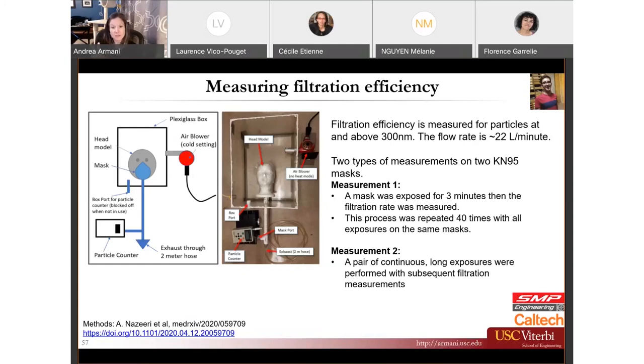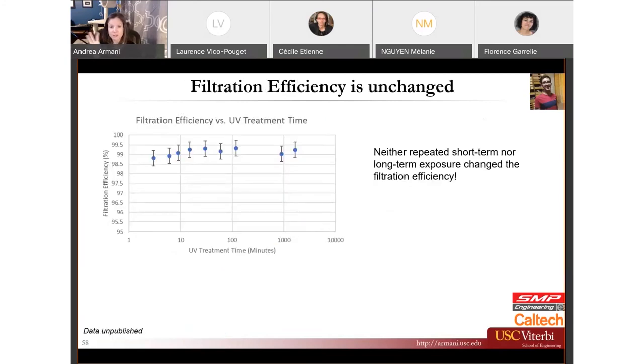Then the second measurement, we took those masks that had already been exposed 40 times and did a pair of continuous, really long exposures. And after each single long exposure, we measured the filtration efficiency. And as you can see, the filtration efficiency versus UV treatment time didn't really change. So neither the short term nor the long term times really affected the filtration efficiency. We thought maybe during the long term the mask would get hot and that might degrade the filtration efficiency, but that didn't happen. And after many long term treatments, no one's going to want to wear this mask again, which is why we stopped.